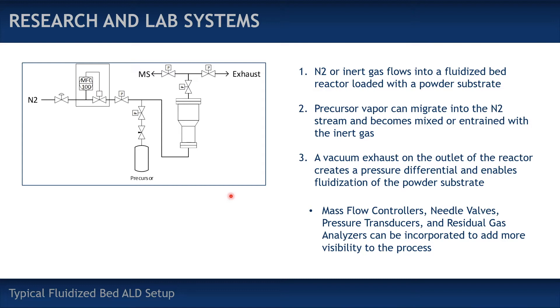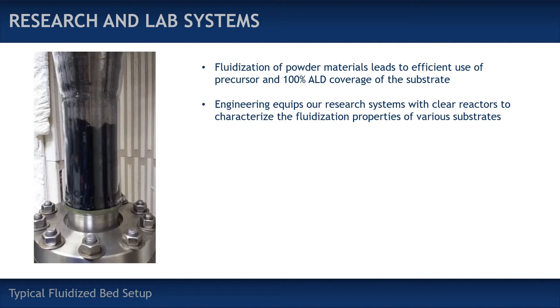That's our general design philosophy for the systems here at Forge Nano. Minimum fluidization is your ideal operating regime for powders, but most powders aren't going to do this easily — many are too small and cohesive to fluidize easily. Our engineering team fabricates clear glass reactors for our scientists so they can fully vet out and characterize the fluidization properties of a challenging powder. More consistent fluidization means reactions happen faster, more repeatably, and precursor usage is more efficient.